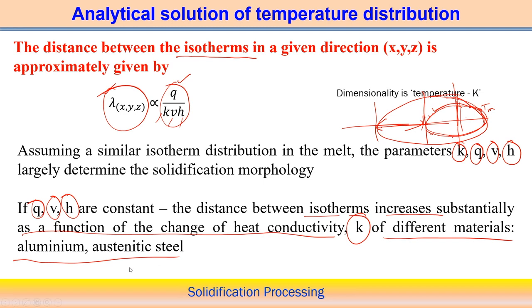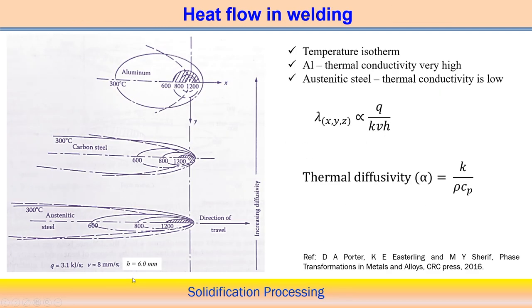Keeping the other parameters the same, if we do the analysis for two different materials, one aluminum and another austenitic steel, we can see how the temperature isotherms are different. Just as an example here, we consider Q equal to 3.1 kilojoule per second, which means kilowatt power is applied here, velocity 8 millimeter per second, and H equal to 6.0 millimeter. With these parameters we see the temperature isotherm. Of course, we are following a certain analytical solution with other assumptions, but approximately we can calculate the temperature isotherm from the heat conduction equation. Here you can see the temperature profile for aluminum, and this is for the austenitic stainless steel.